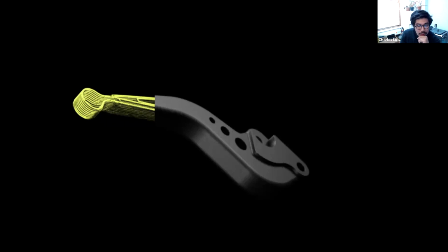Difference in composition between Onyx and Onyx FR. I think the fiber fraction is pretty similar. We just added an anti-burning additive, or rather an additive which undergoes an exothermic reaction and stops burning. That's what it is. Why is the Young's modulus different? It could be because of the additive. It also has a different base polymer. So the fibers are the same. It's a different base polymer. So they're nylons, just different types of nylons.